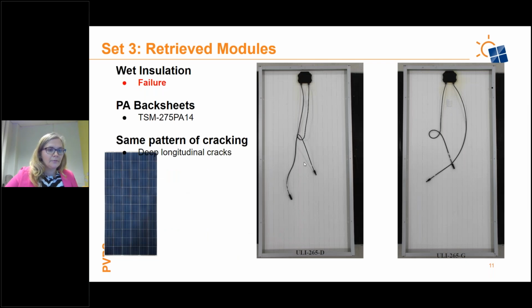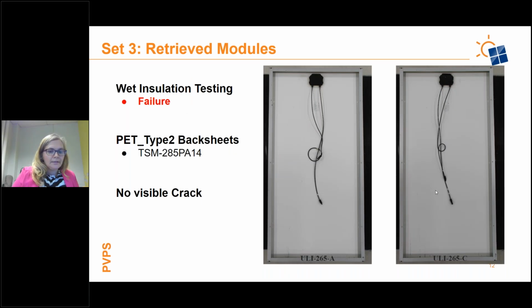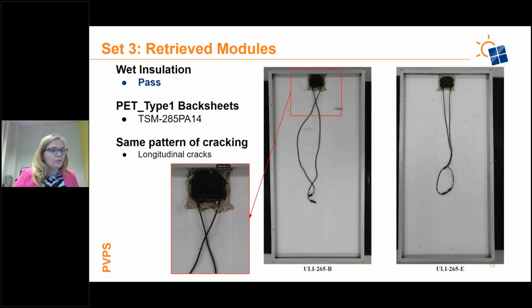So what you see here is that for the polyamide backsheets, we have severe longitudinal cracks. And for the PET backsheets that failed the wet insulation testing, there were no particular cracks that we saw on these backsheets. And then these were the two PET backsheets that were repaired. Here's a little close-up picture; you can see they were repaired right around the junction box and then down the module. This is obviously a tape that was put on, and then they were still out in the field for a while and then taken off the field after repairing.